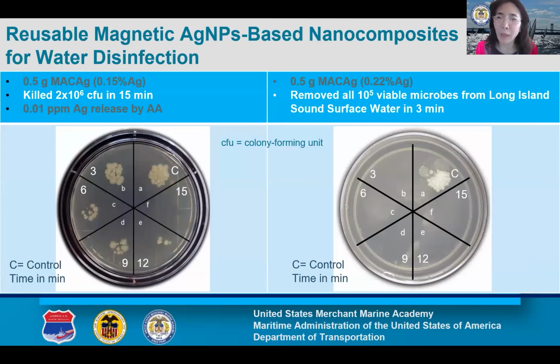Our initial effort involved incorporating silver nanoparticles and magnetite nanoparticles onto an activated carbon matrix, which we've termed MAC-Ag. Our MAC-Ag product proved highly effective for water disinfection. For instance, 0.5 grams of MAC-Ag containing 0.15% silver was shown to kill 2 × 10⁶ colony forming units, or CFU, in just 15 minutes. A sample with 0.22% silver was shown to remove all 10⁵ viable microbes from Long Island Sound surface water within 3 minutes.